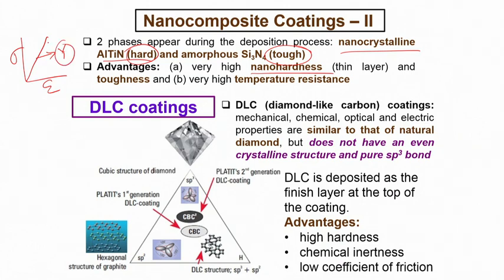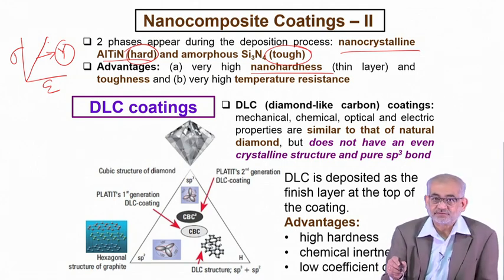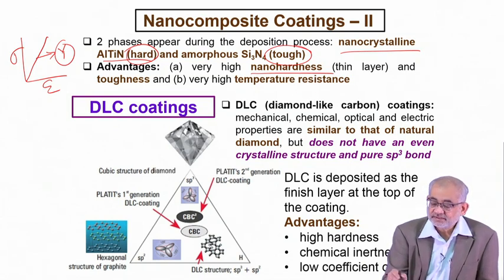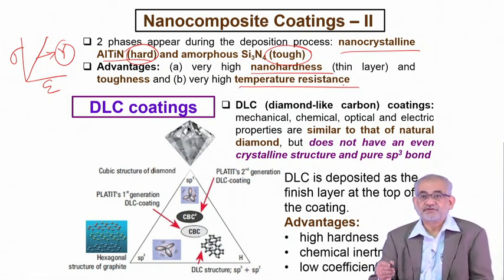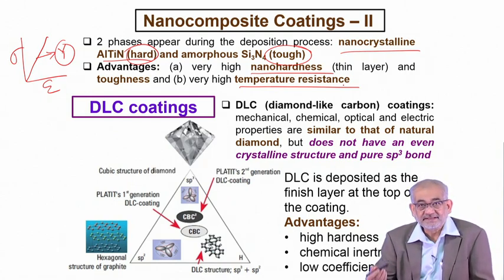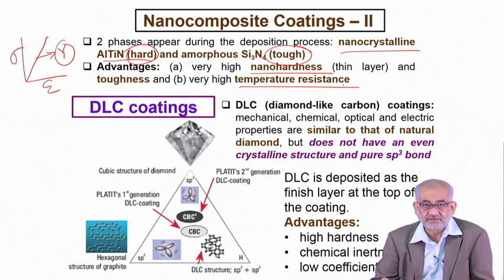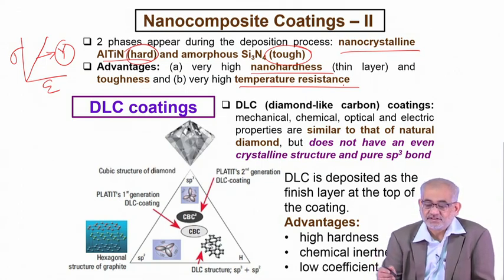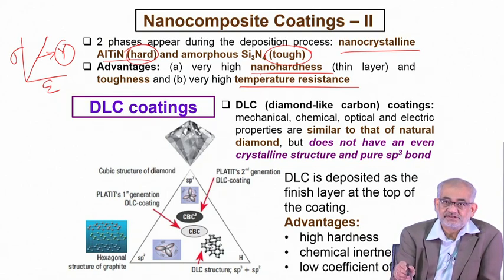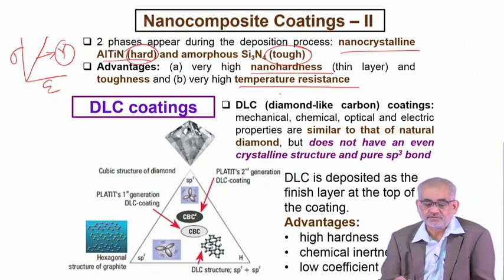and from this proportionality limit you actually can also calculate the Young's modulus. So using this nano indentation technique, one can not only measure the hardness but also the elastic modulus of the material. These materials also produce very high temperature resistance because of the chemical nature of the deposit that you develop. It's not pure metal, it's actually compound, and these compounds have very high melting temperatures. They are also very strongly bonded compounds, so they are resistant to heating. And this is not isothermal heating, this is basically contact heating, adiabatic heating during the high speed cutting operations. And so the dimension of the tool is better retained by application of such nanocomposite coatings.